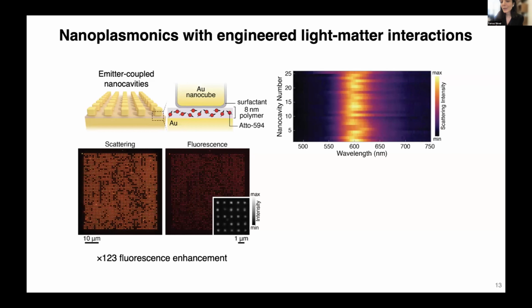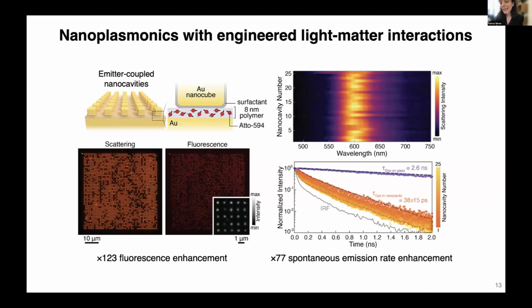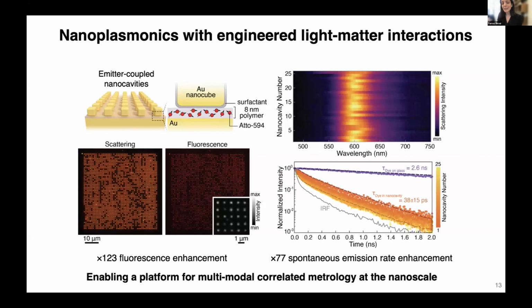Then we can see that the individual devices give fluorescence enhancement, and we characterize that to be on the order of 123 times. Now, the technique also allows us to do correlated studies. So the same 5 by 5 array of devices that we've measured here in terms of scattering response, we can then use to do fluorescence spectroscopy, and in particular measure their decay time, showing about 77 times enhancement of spontaneous emission rate. So a point to keep in mind here, such techniques, in addition to having contributions to device fabrication and enabling new device platforms, again introduce a new path for us to be able to do correlated multimodal spectroscopy. And oftentimes multimodal spectroscopy is necessary at such scale to be able to best understand the effect of multi-physics on the performance of the devices.